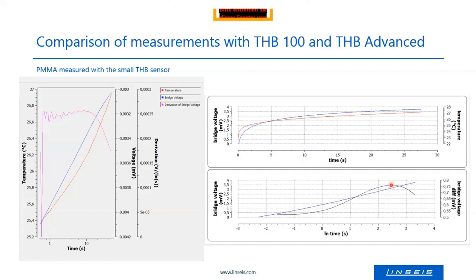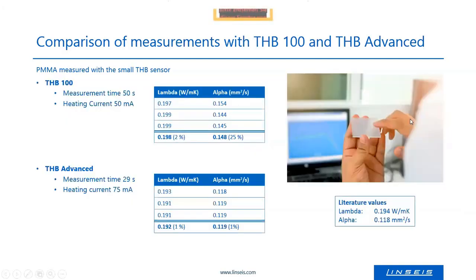The same signal is here on the bottom part of the new instrument measurement. You see here the blue line, bridge voltage, the derivative of this blue line. And here on the upper part, the red line is the temperature increase during the measurement. And when we compare the data, we see both instruments are very good for the thermal conductivity.